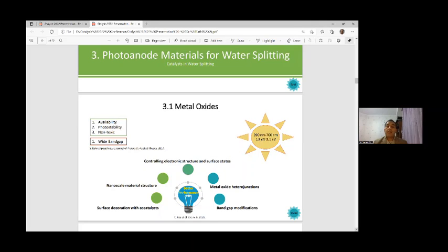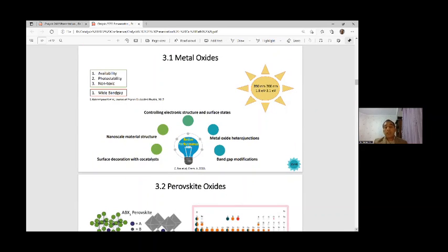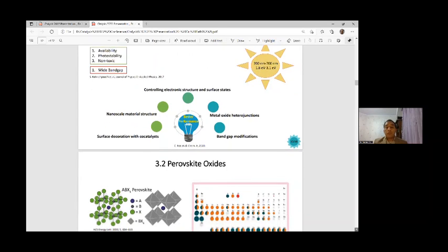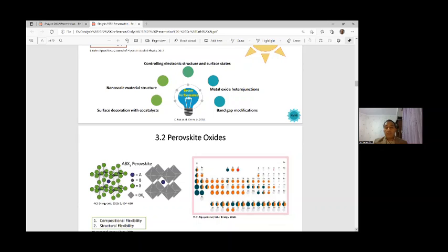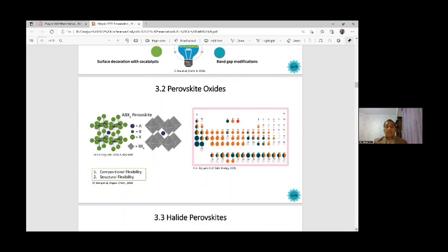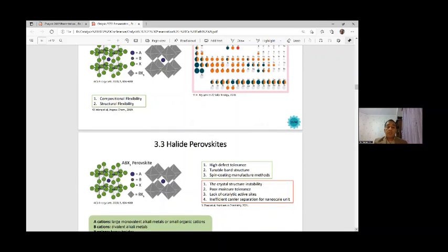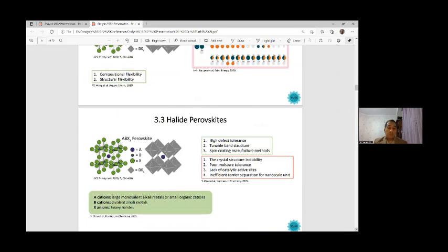Surface decoration with catalysts and metal oxide heterojunctions are important issues for us, as are band gap modifications. Often we need to do band gap engineering to obtain a suitable band gap for sunlight absorption. At the next step, we have perovskite oxides as suitable candidates for photoanode materials. Perovskite structures usually have advantages such as compositional and structural flexibility. Halide perovskites are usually used in this slide.